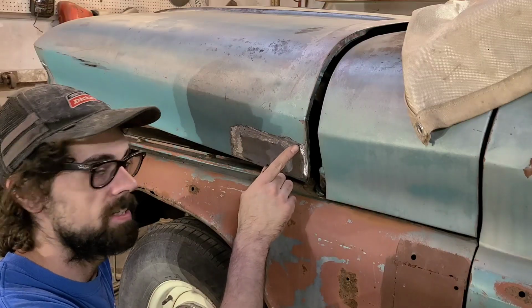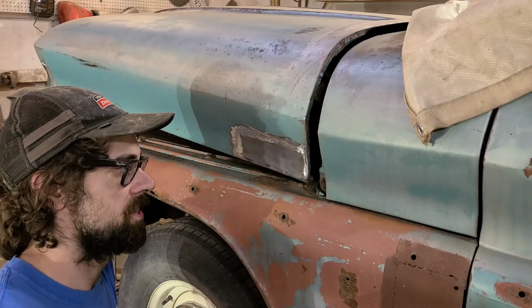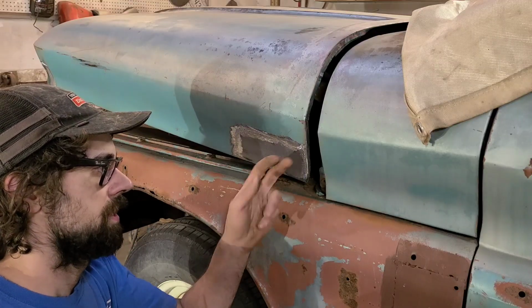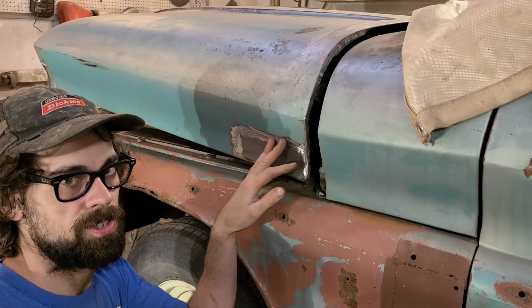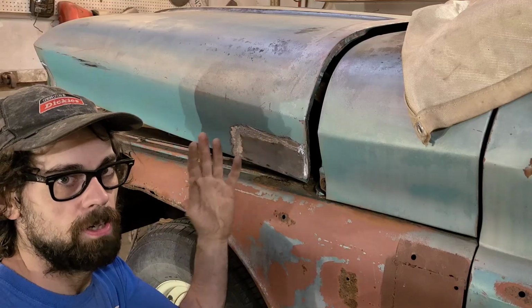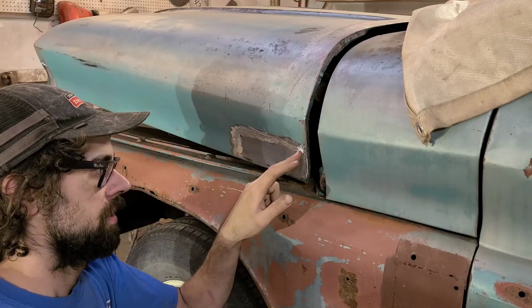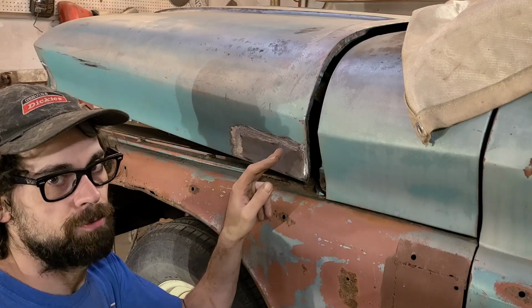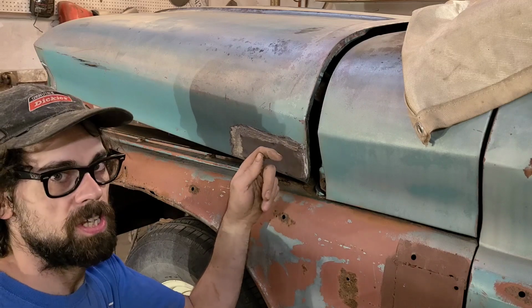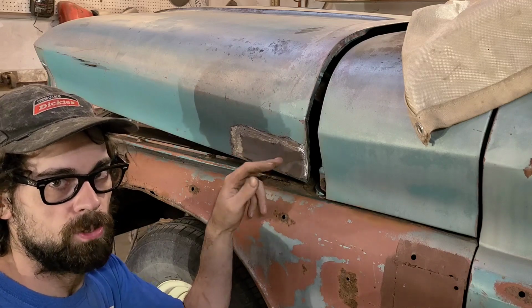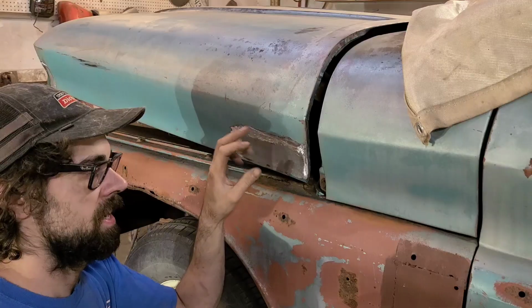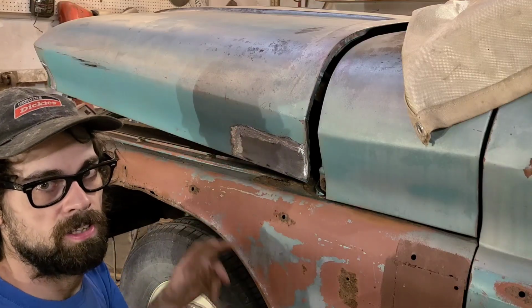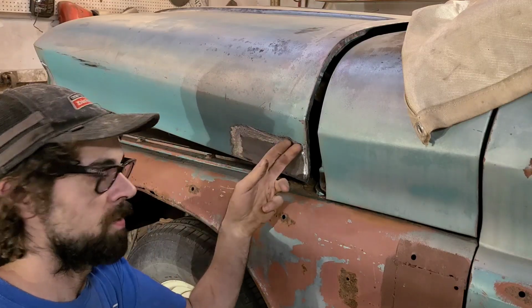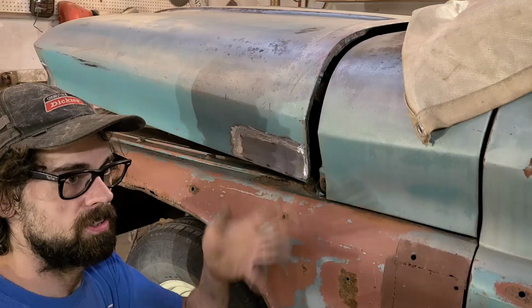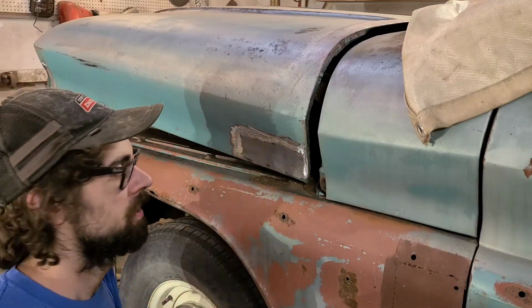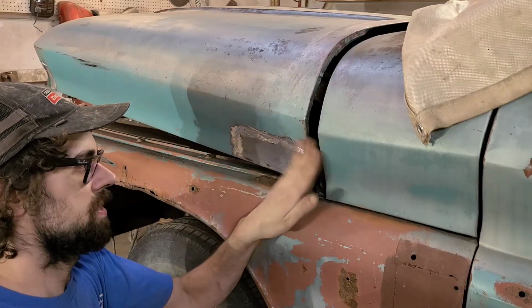Another reason that I grind down these tack welds, and the most important reason before I finish weld, is that when I go back and stitch weld this with what is hopefully going to be a full penetration weld, I want to make sure that I'm getting full penetration. If I have a tack weld sticking up, it's going to create a cold spot on my new weld and an inconsistent area. We want consistency, and we don't want any cold spots on our welds because those can lead to pinholes or cracks. So that's the main reason I do this.